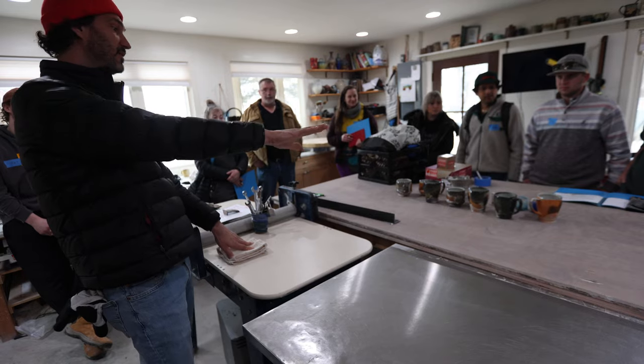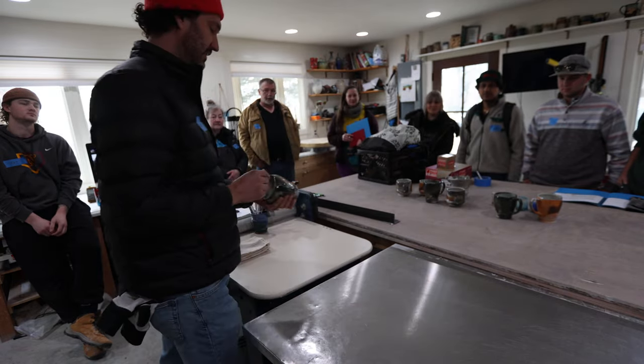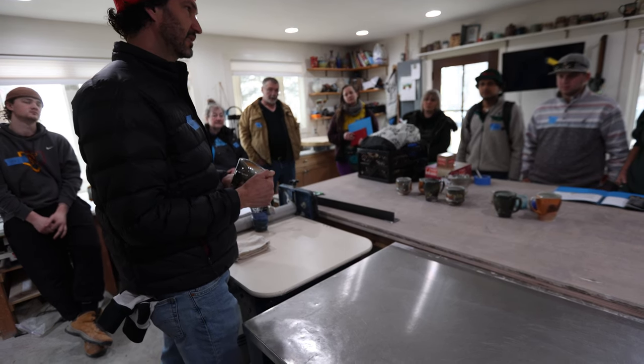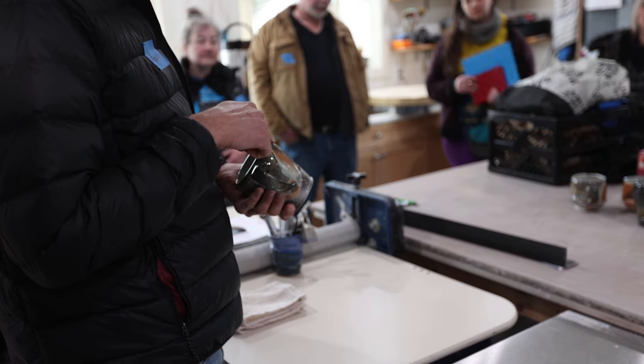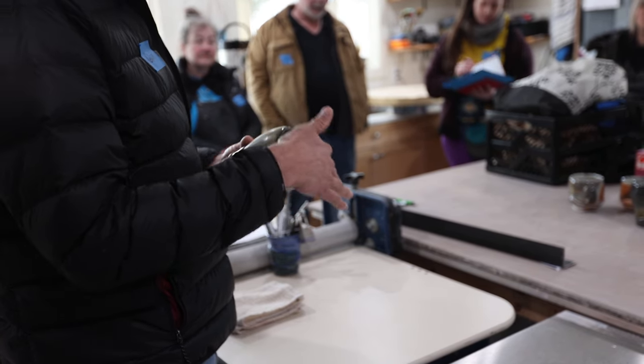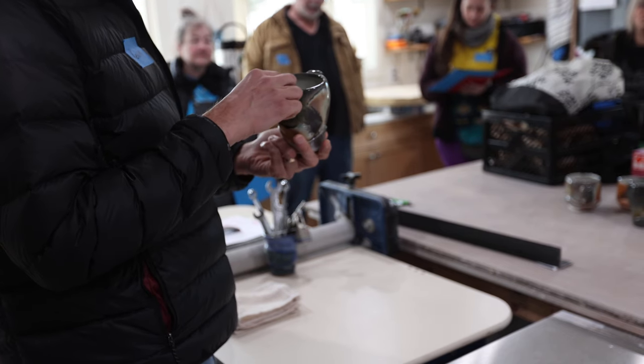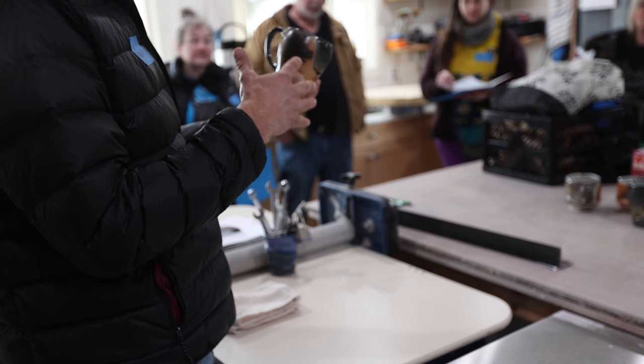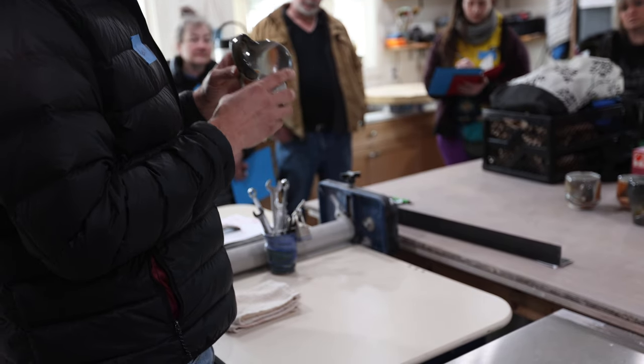And these have no glaze on them. These pieces here are all flashing slip. This is a Nara porcelain from Aardvark. And then there's a flashing slip applied here with the Mocha diffusion technique on top. And then glaze on the inside only, just to line it. Okay. And then the rest is achieved by the soda vapor in the kiln and the yellow flashing slip. So this doesn't have any glaze.